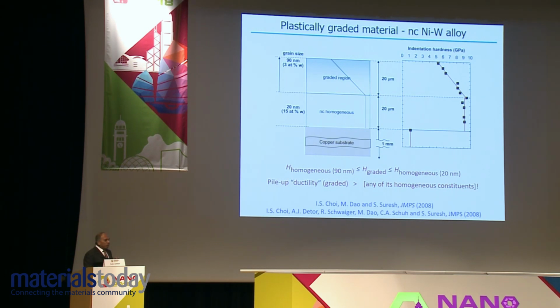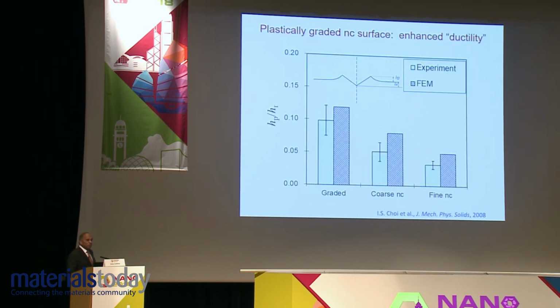And then we found the following, that when you indent a graded material as opposed to any of the homogeneous materials, including the composite of different compositions, the evidence of ductility in an indentation test, which is the pileup around the indenter, is the greatest in the case of the graded material, because of the way you distribute the loads during indentation into the substrate for a particular mechanism. So this gave us an opportunity to look at plastically graded materials with nano gradients at the surface. And here is the result that we found about 10 years ago.